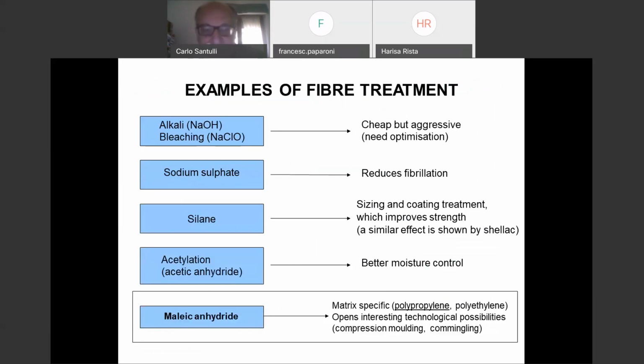Some examples of fiber treatment. We can treat them aggressively, this is what was usually done in textiles. So the treatment with alkali, like sodium hydroxide, or bleaching, which not only makes them more regular, by matter transportation basically, but it makes them also somehow whiter. Then we have other treatments with sodium sulfate, which reduces the fibrillation.